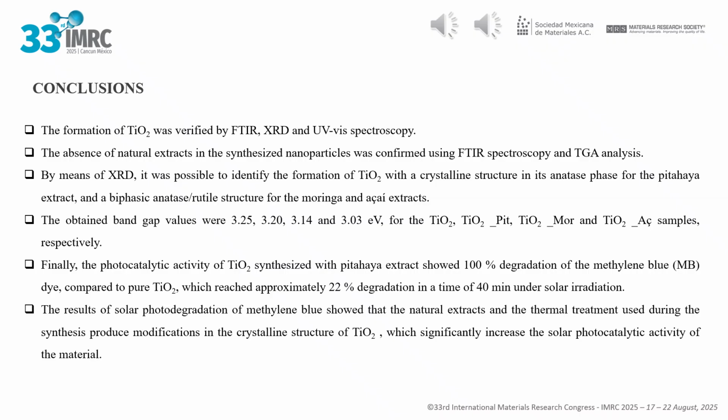The obtained band gap values were 3.25, 3.20, 3.14 and 3.03 eV, for the TiO2, TiO2_pit, TiO2_mor and TiO2_AC samples, respectively.